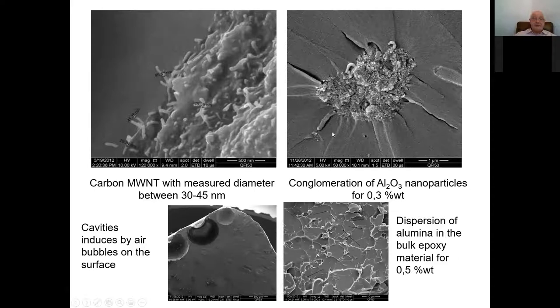And this is unfortunately a big problem because, talking about nanotubes, they can conglomerate like this, and this is bad news. Of course, you can have a nanotube here, which came out, and the other one, you have somewhere between 30 and 45 nanometer diameter. But conglomeration is not good because conglomeration, as it is here for some alumina nanoparticle, 0.3%, will be a local stress raiser, and the crack will initiate from here.